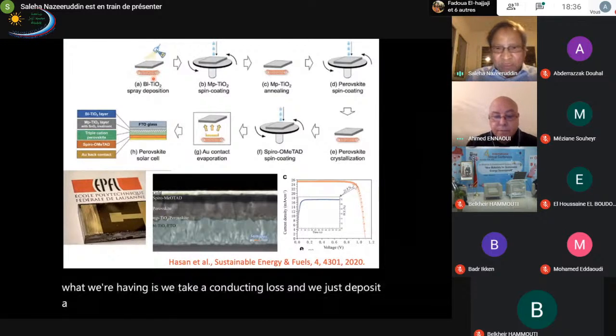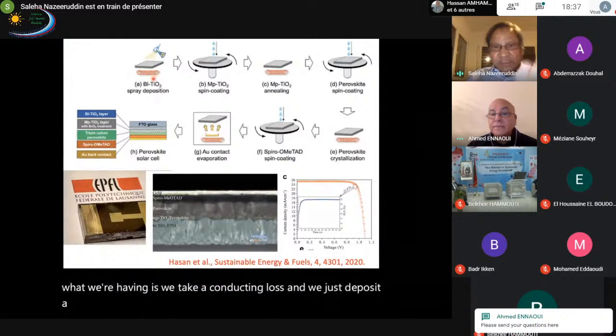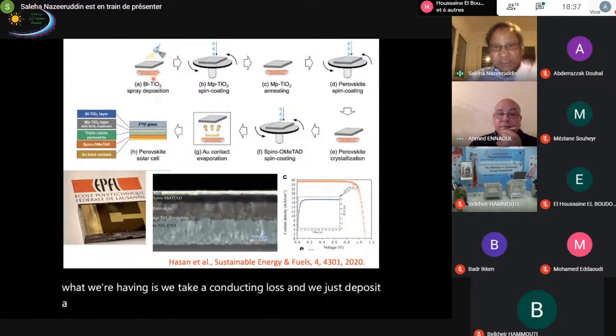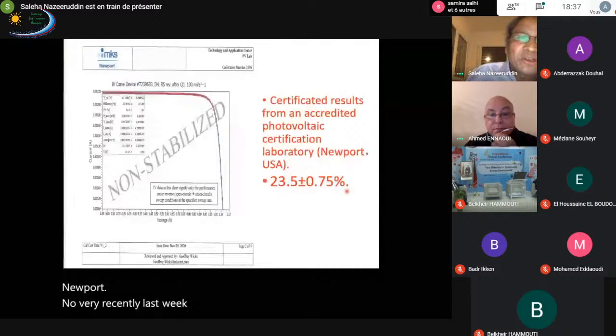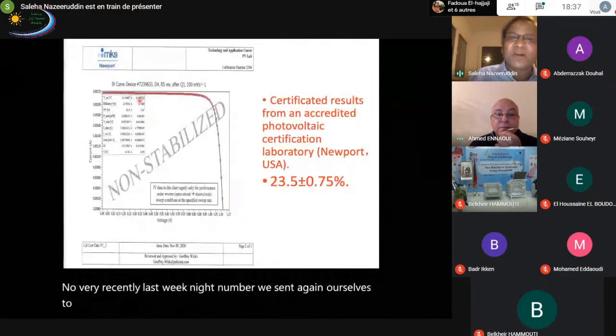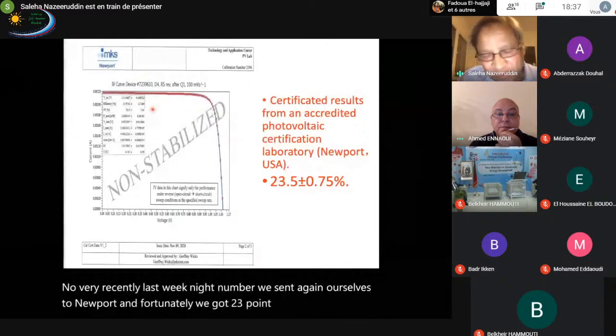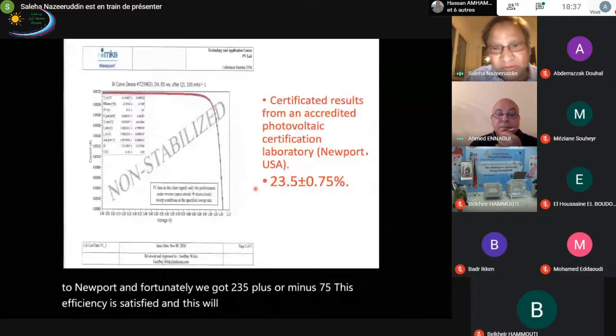The cross-sectional image is shown here, which represents the previous description. You have titanium dioxide as the electron transport material, perovskite as the absorber material, spiro-OMeTAD as the hole transporting material, and gold as the contact. With this type of cell in the laboratory, we get 22% efficiency, which we also certified at NREL. Very recently, last week, on 9th November, we sent our cells again to Newport, and fortunately we got 23.5 plus or minus 0.75. This efficiency is certified, and we will be putting up a startup very soon in the Valley using this technology.